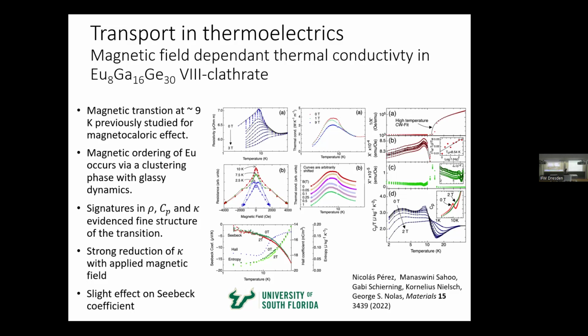The game here was to introduce a magnetic component, and the question proposed by the collaborator in Florida was to study if there was, due to magnetic ordering, which happens in this material, some change in thermoelectric properties. We were expecting to see some change in the Seebeck coefficient. We didn't find much of it, but what we saw was a strong reduction in the thermal conductivity when the material became ferromagnetic. The clathrate, if you know, is a cage structure, with voids where nothing is, and inside these voids you may place some things.